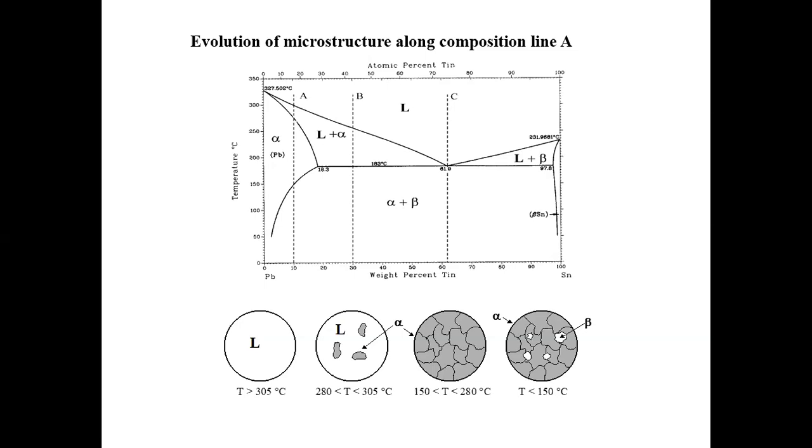Yeah. Okay, so we're going to explain why this is the case later, because this occurs through a nucleation process, and we'll show later that in a solid solution, when you talk about nucleation, you have to worry about the diffusion. You also have to worry about the elastic energy or the mismatch of the lattices. It turns out that whenever you want to insert a solid with a different volume than the other solid, it's better to do this on the grain boundary where you have a lot of packing defects. This is going to release the stress or strain energy introduced by this particular process.